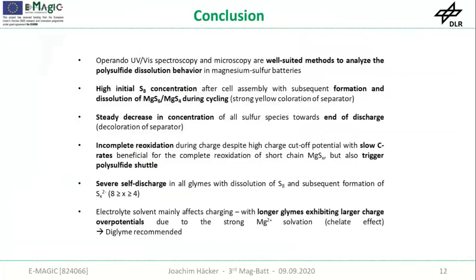With this, I want to conclude: operando UV spectroscopy and microscopy are well-suited methods to study the polysulfide dissolution behavior. And with this method, we found that even directly after cell assembly, there is a high initial elemental sulfur concentration in the cell. And during discharge, MgS6 and MgS4 are formed, and their concentration decreases again towards the end of the discharge.